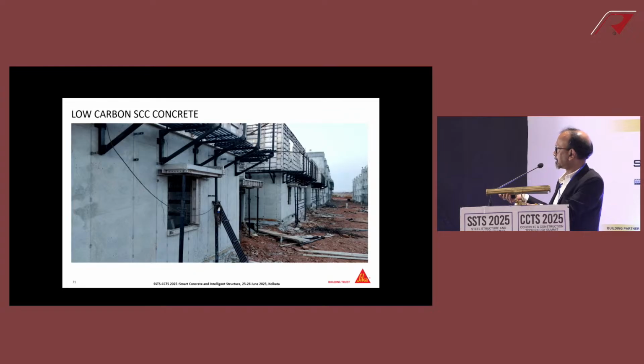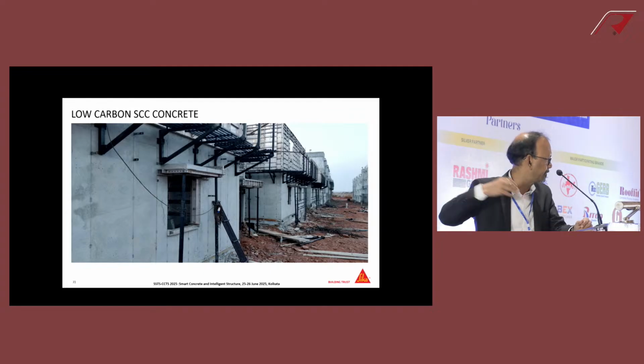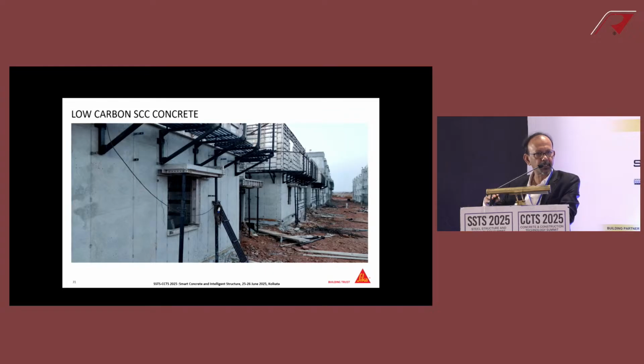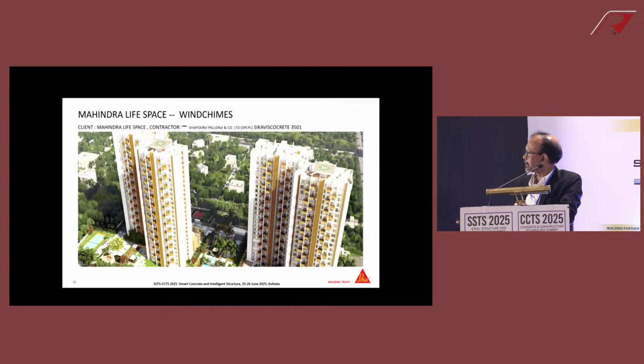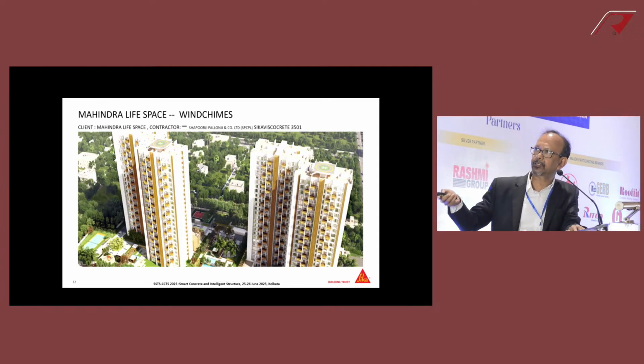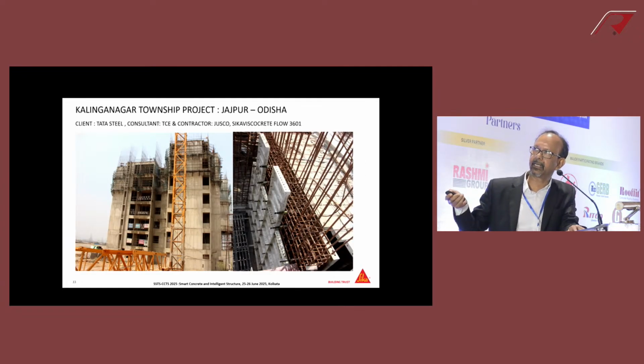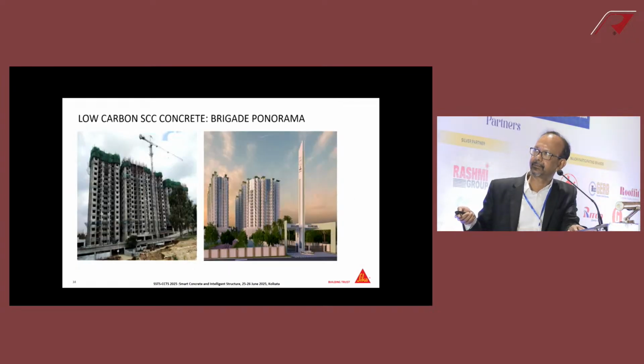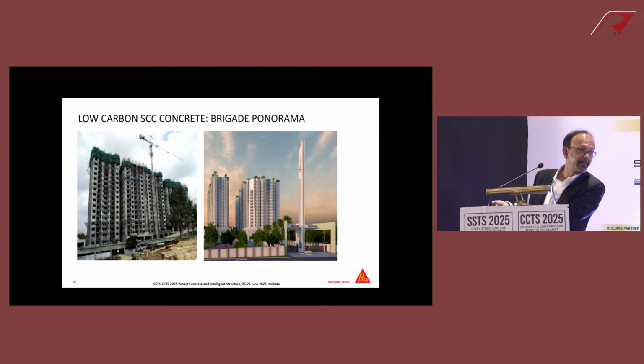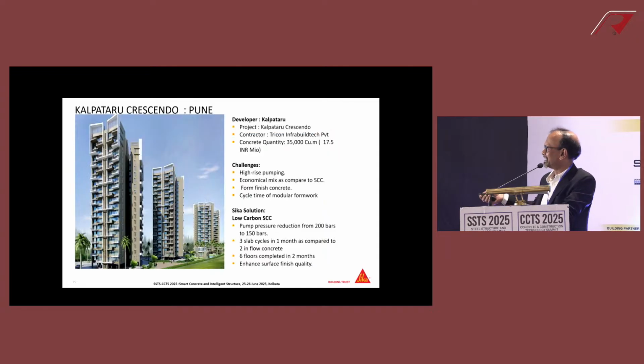So give you some examples. This surprisingly is a low cost slum development, because we always think such concrete can only be used in complex structures and all. Bangalore slum rehab, they went for 2 massive housings, and they used this with formwork because they did not have high capital expenditure, so they used only 2 or 3 sets of formwork to roll it out for the entire area. So that is also cost saving, energy saving. Again, on the high end, you have Mahindra Lifespace, also used with low carbon SCC. Then at Orissa, again, these are 2 pictures, one traditional and one with SCC. Then this is in Bangalore. And people from Bangalore will also be very impressed. Okay, this is again in Pune. So all across India, low carbon SCC has already been laid.